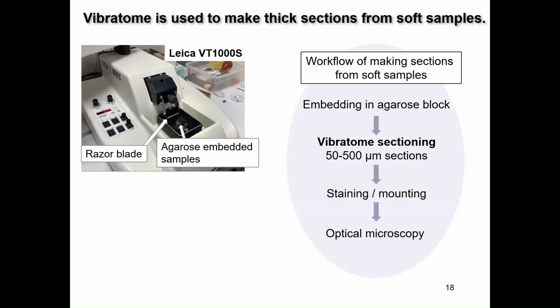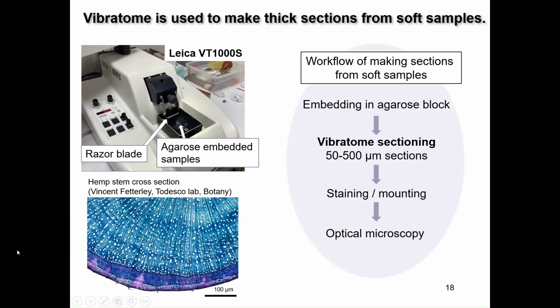And after sections are made, they tend to float in a water bath. So we use a brush to collect them and then mount them on a glass slide. And you can stain them, and you can also do optical microscopy. So this is an example of plant stem cross sections. The cross section was made with vibratome and then stained with Toluidine blue, and then was imaged with Olympus BX53 microscope.